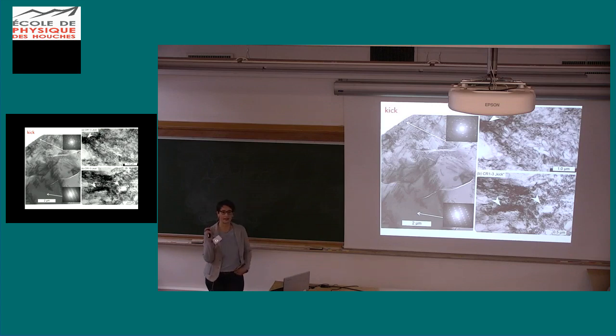So it's tiny microlites which have a more or less random crystallographic orientation. And so this is only very close, very localized and very heterogeneous deformation along such a crack. But if you go some distance from the crack, we basically see an undistorted crystal. So we have strongly localized deformation, glide controlled fracturing, so it's a combined fracturing and dislocation glide controlled deformation, low temperature plasticity, what we heard yesterday and already on Monday.